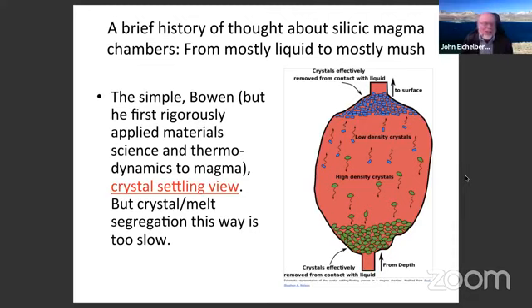Well, probably the earliest ideas were that these were mostly liquid bodies that chemically evolved because the crystals are of different density than the melt, and therefore by gravity you get separation of crystals and melt, and the bulk composition changes because of that during crystallization. And that certainly happens where melt is very fluid in basaltic systems. But in rhyolitic systems, the melt is very viscous and the crystals are very small and not so much different in density from the melt. So you've got everything working against you, and basically hell freezes over, or more accurately, the magma chamber freezes over before the crystals can move very much.